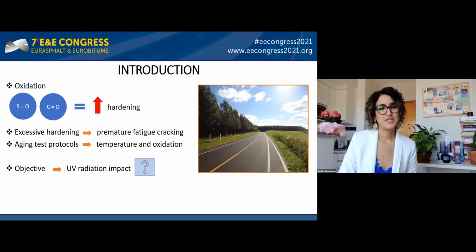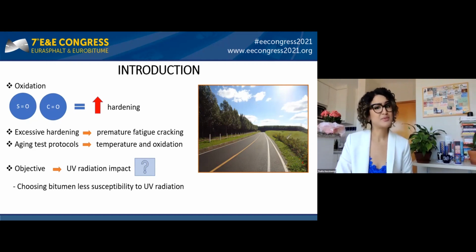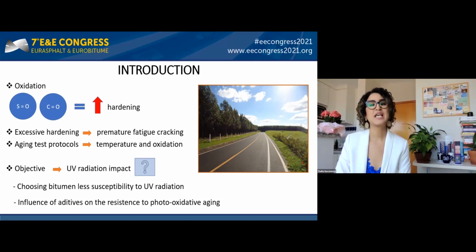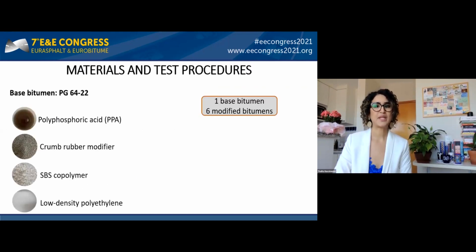It is important to choose bitumen less susceptible to photooxidative aging, especially in regions where intense UV radiation throughout the years is present, as in Brazil. Studies including various modified bitumens are necessary, as the influence of additives on the resistance to photooxidative aging is still not entirely known. The experimental plan was performed using a neat bitumen and 6 modified bitumens with polyphosphoric acid, PPA, crumb rubber obtained from discarded tires, SBS copolymer, and low-density polyethylene.